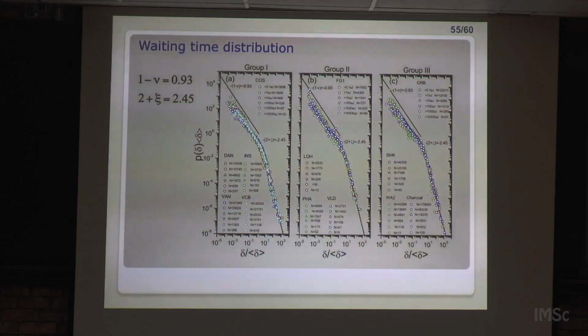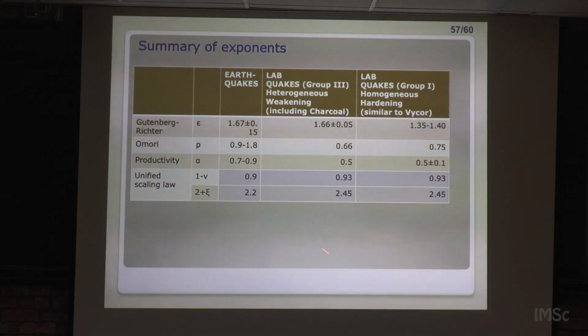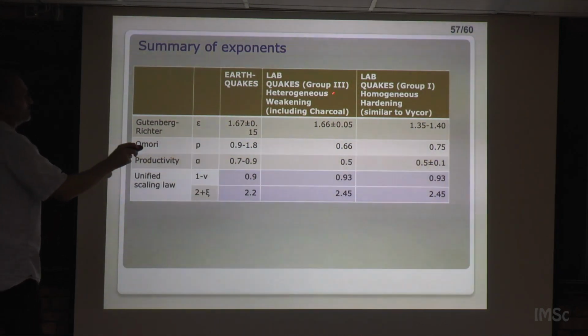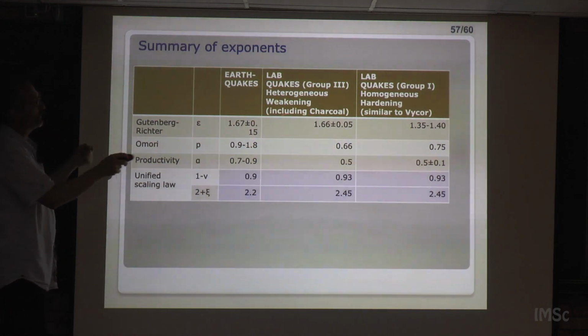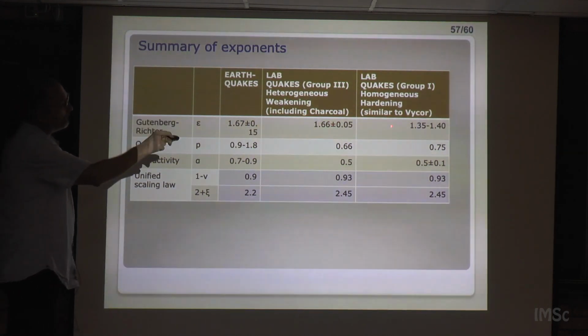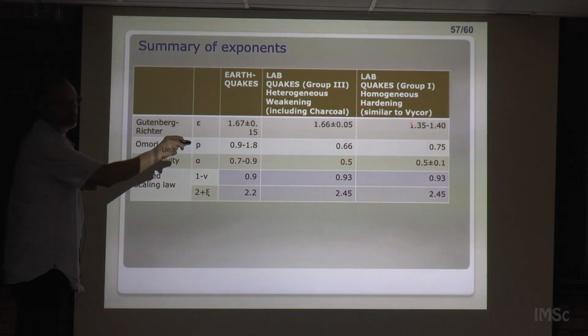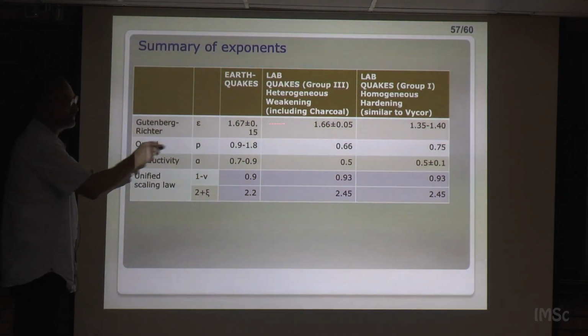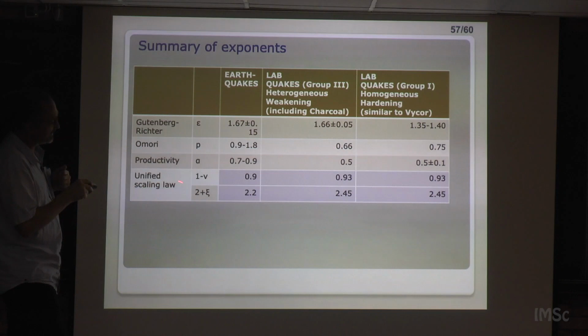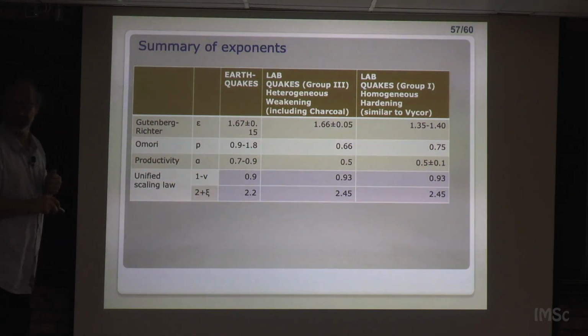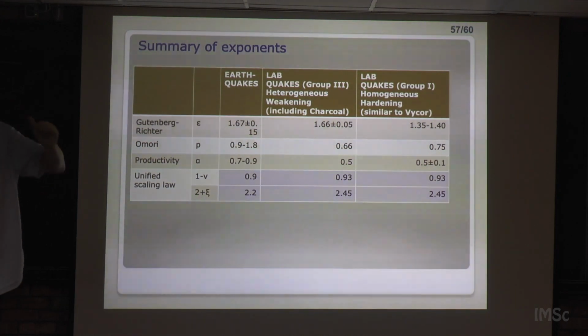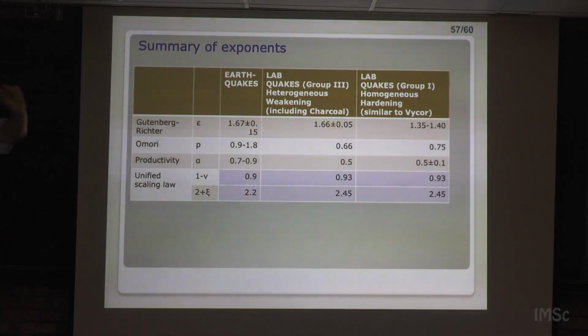Sorry, because I was rather fast, but so this is a summary of the exponents. Essentially, earthquakes and heterogeneous samples that show weakening have the same exponents. Samples that show hardening have the Vycor exponent, 1.35. Here it is 1.66. And then the other interesting message is that the 1 minus nu and 2 plus xi are the same everywhere, always. So this law, this double power law, seems to be really very universal, despite the Gutenberg-Richter law being different from one class to the other.